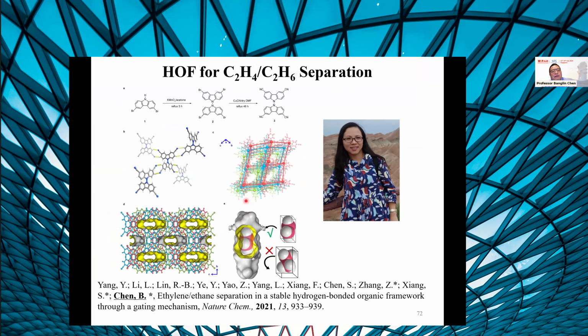And unbelievably, even beyond our imagination, we can use this very simple organic linker with cyanide. And typically, no one would realize this. Even using this cyanide compound, we are able to stabilize the framework. In fact, this framework is very stable because of the interpenetration and also the pi-pi interactions, although the hydrogen bonding is comparatively weak.